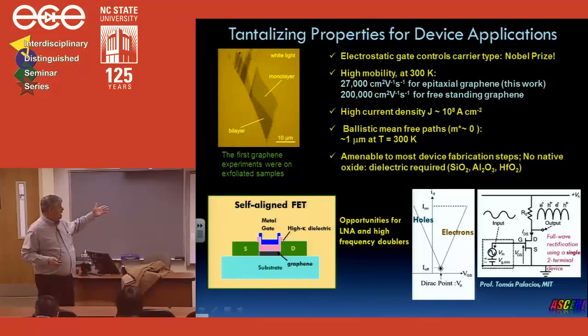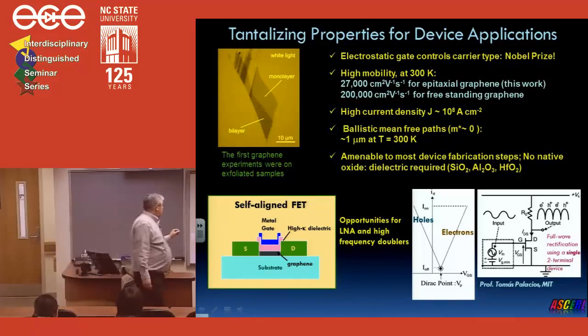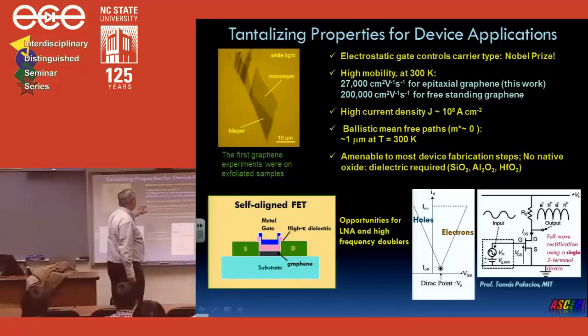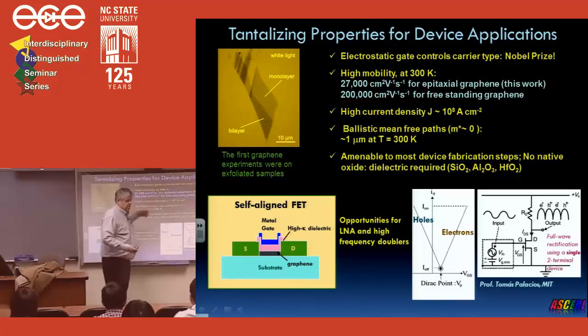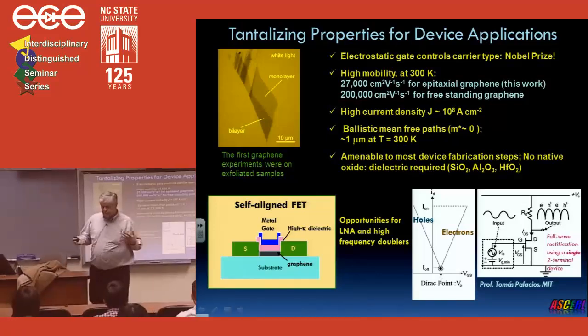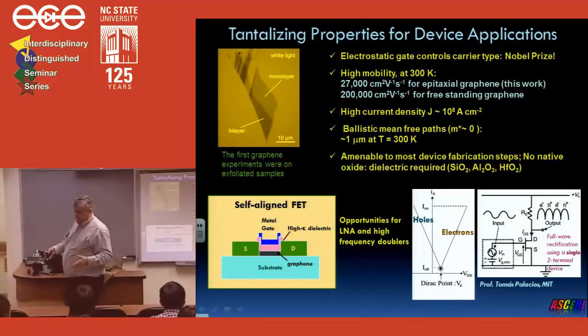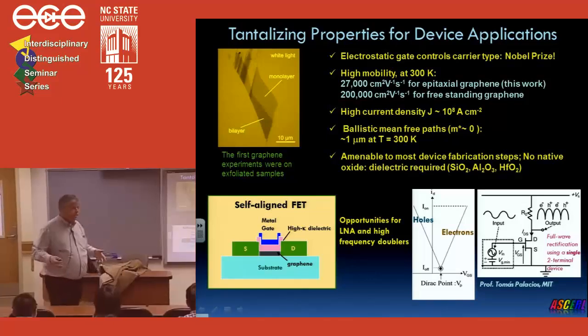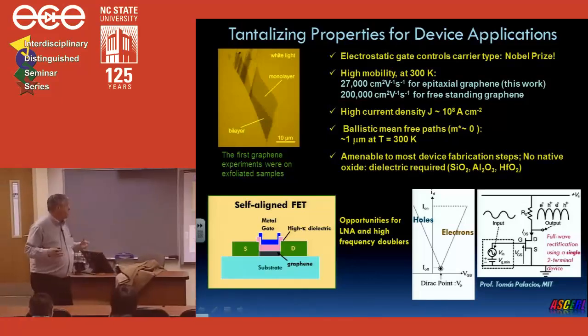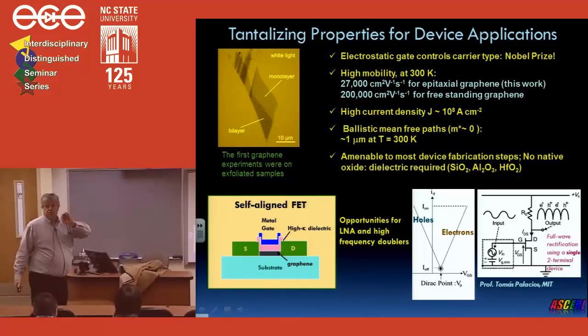It has high mobilities. Actually, the mobilities have been measured to be in the hundreds of thousands for freestanding graphene, and that decouples the graphene from the surface that it resides upon, and the surface is limiting the transport of those charge carriers because of various scattering mechanisms. It supports very high current densities. It's all surface. There's no volume. It's just a single sheet of atoms.